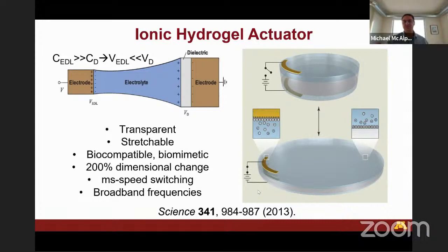And so we wanted to translate this to our 3D printing platform by basically printing the entire structure. The tape can't be 3D printed, but we can replace it with silicone. And we can use the same silicone that we use in the organ model, so that the entire structure replicates the same softness of the organ model and basically blends into the model. So we 3D printed the ionic hydrogel here.